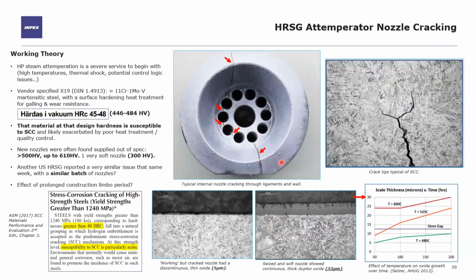We've now had 2 different metallurgists section and mount cracked nozzles, and they both agree that the cracking morphology takes the form of stress corrosion cracking rather than, say, a fatigue mechanism. And again, there's a lot more to an attemperator than just metallurgy, and we're working on the process side as well, but our findings we thought were pretty compelling.